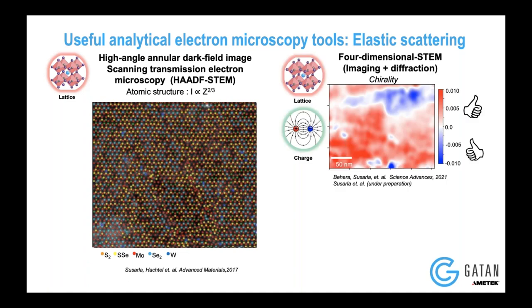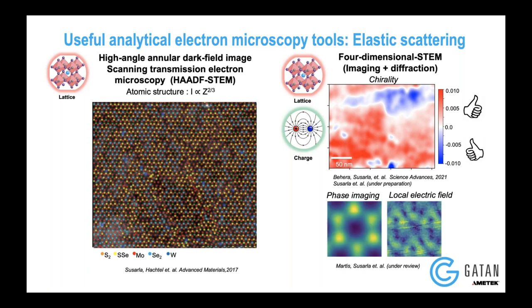In that sense, you need additional techniques to understand the three-dimensional picture of what is happening structurally. 4D-STEM is actually a very useful technique to quantify what you see in your STEM images. For example, this was a very unique case where we actually measured the strain in these topological structures in oxides in order to unravel the chiral domain boundaries in the material. Similarly, you can tune your convergence angle to make your probe very small, and if you make your probe very small, it's sensitive to the local nuclear potential, allowing phase contrast imaging and measurement of the local electric field.